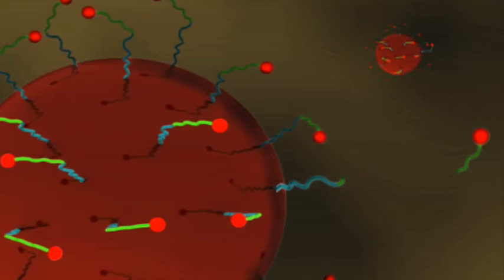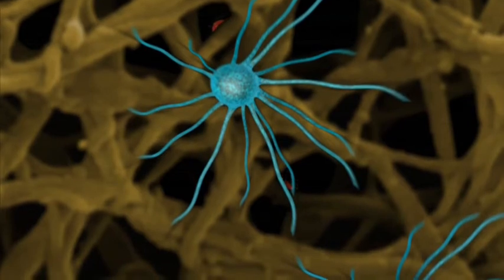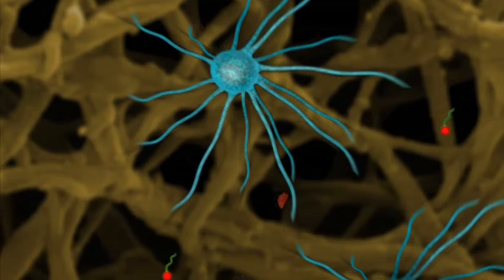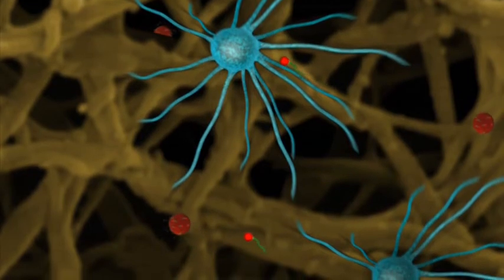Here we report on the synthesis of a tumor-activated prodrug composed of doxorubicin attached to polyethylene glycol through two matrix metalloprotease 2 cleavable peptides, namely A and B. Both peptides contain the glycine-leucine sequence, which is highly sensitive to matrix metalloprotease action.